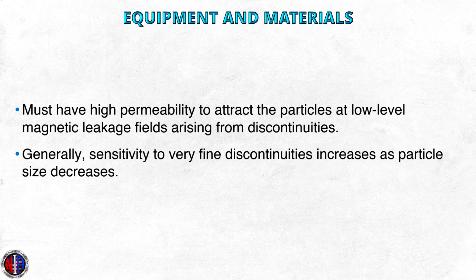The properties of different materials, shapes, and types vary widely, but all must have the highest possible permeability to attract the particles at low-level magnetic leakage fields arising from discontinuities. The size and shape of magnetic particles play an important role in how they behave. Generally, sensitivity to very fine discontinuities increases as particle size decreases. However, very small particles may adhere to the surface where there is no leakage field and thus form an objectionable background. Conversely, large, heavy particles are not likely to be attracted and held by a weak leakage field as they move over the object surface.